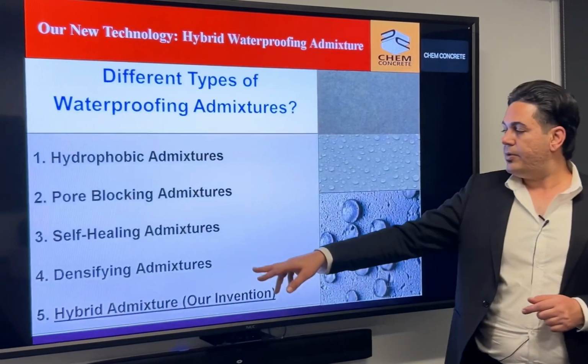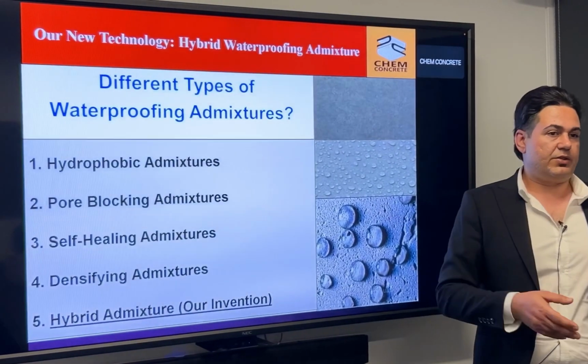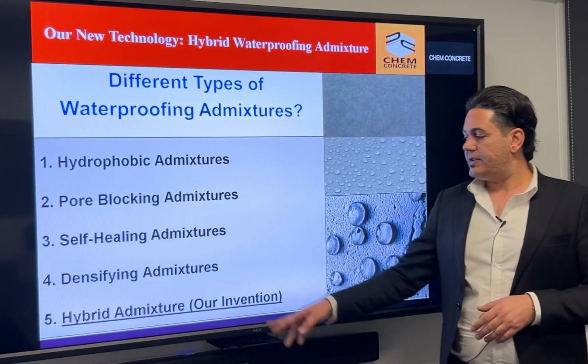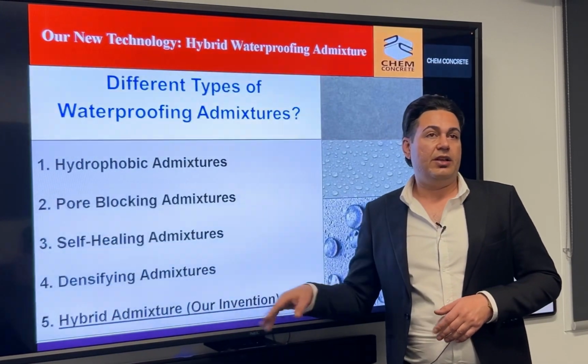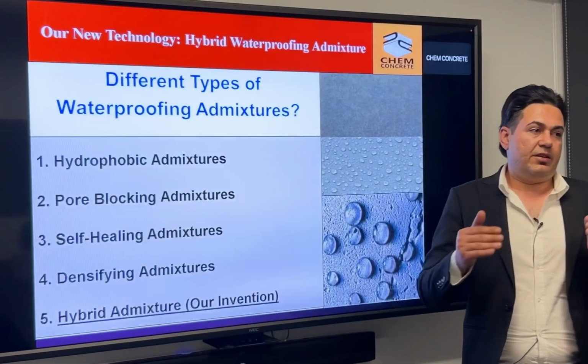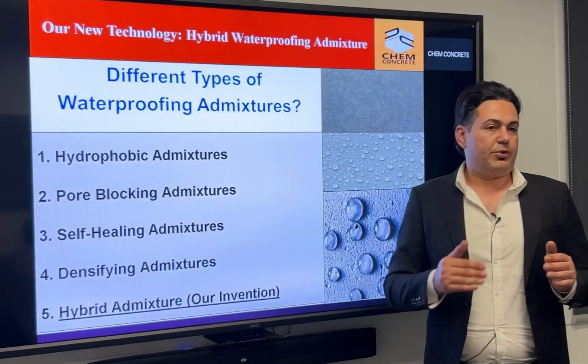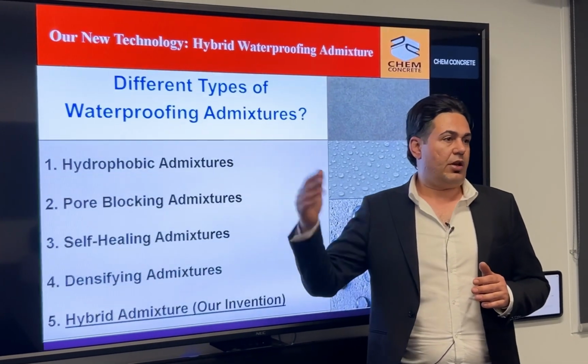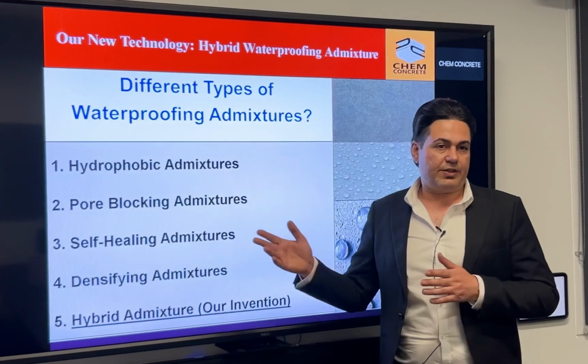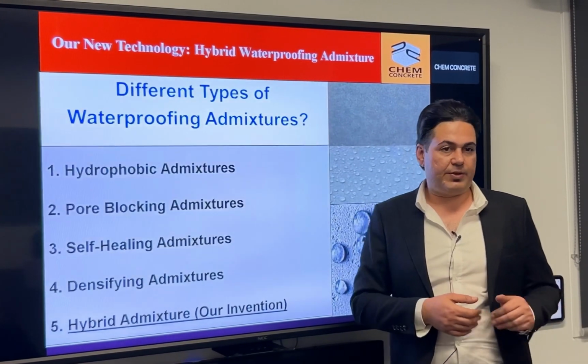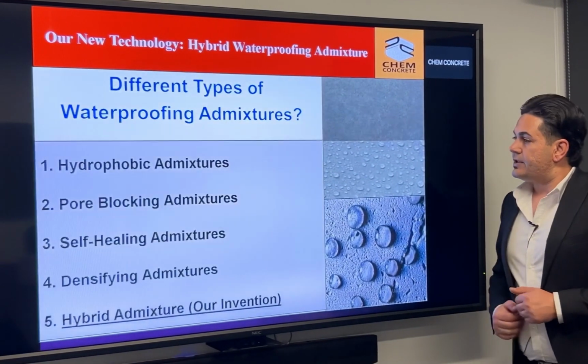So that's why independent testing as well as our in-house testing has shown that this admixture, depending on the dosage used, can reduce the water absorption and permeability by 70 to 95%, which is a huge difference compared to 10% or 5%. Next slide, please.